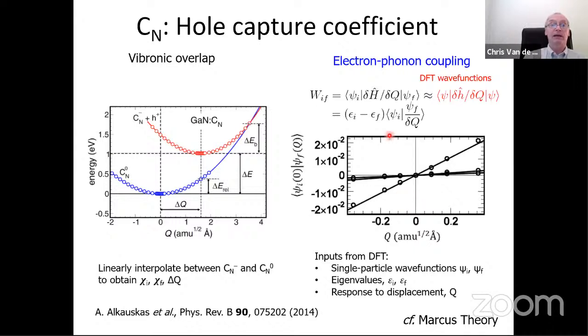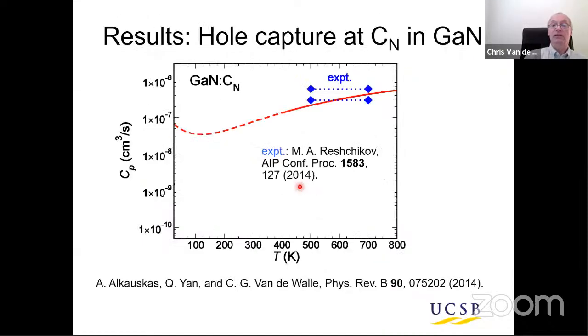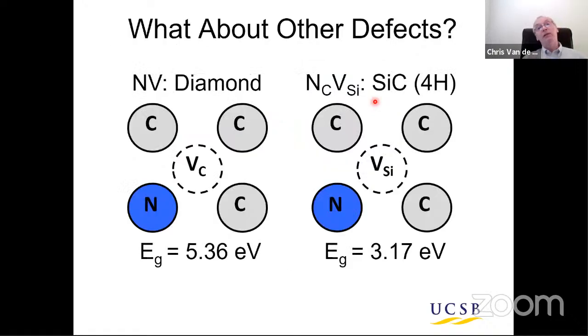Okay, so again, for my example of the carbon in gallium nitride, we can actually, in addition to analyzing the radiative transitions, also analyze non-radiative transitions. And this is a capture coefficient that describes the rate at which holes would be captured. And the calculated value, which is plotted here as a function of temperature, agrees remarkably well with the experimental measurements that were performed within this temperature range. So again, this serves as a benchmark to show that we can actually calculate these non-radiative rates in this case with high accuracy. Okay. So that's kind of our toolbox.